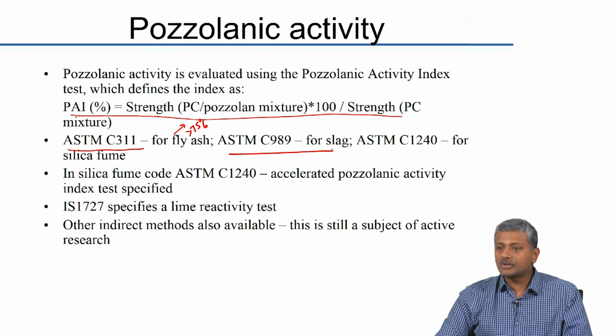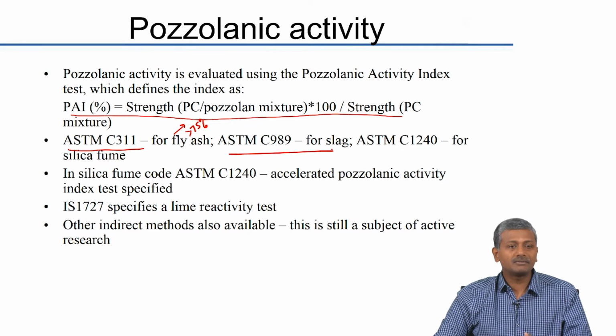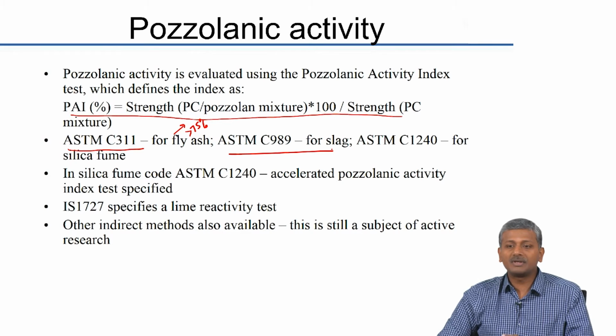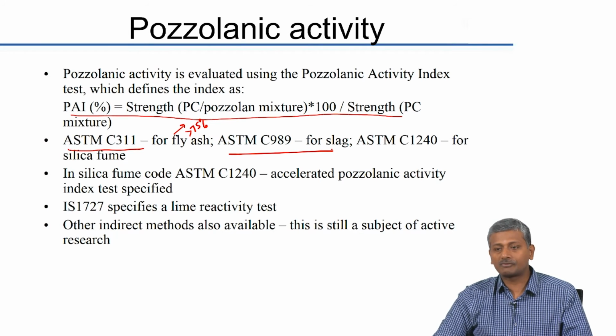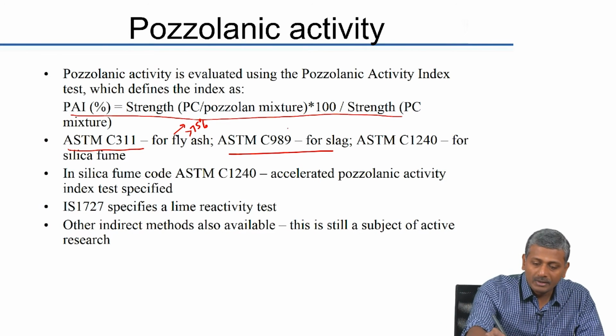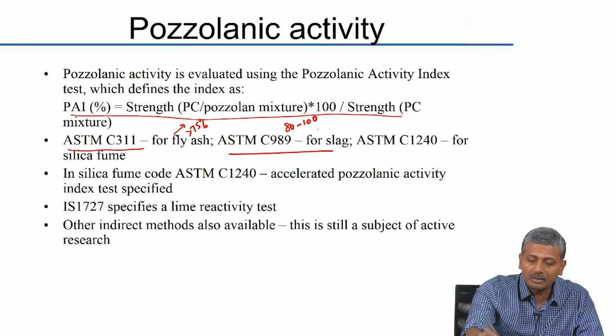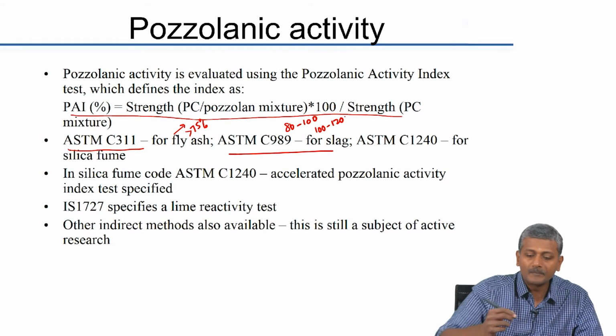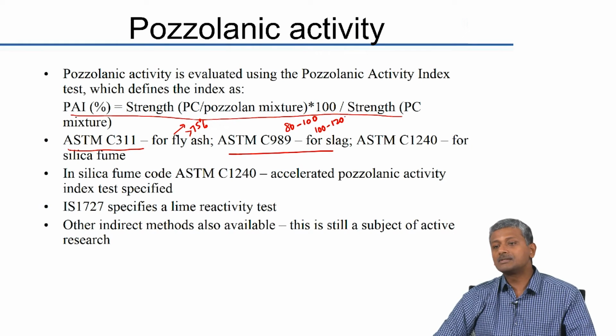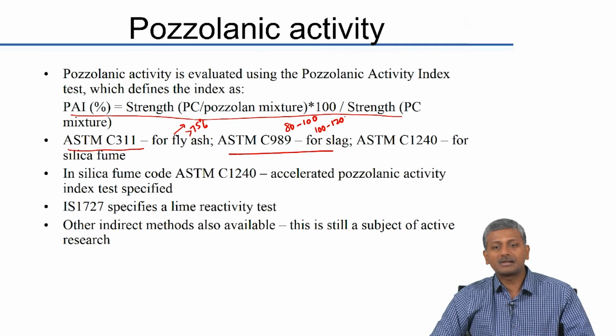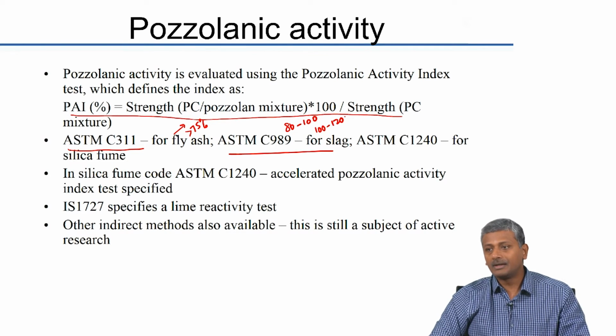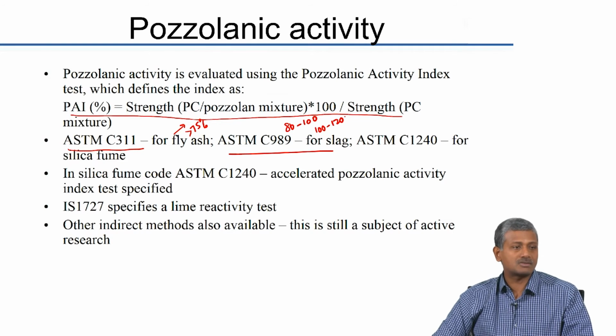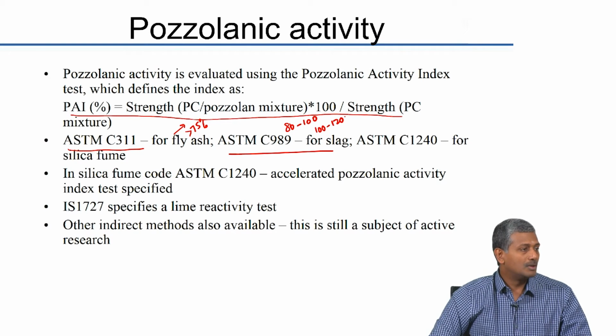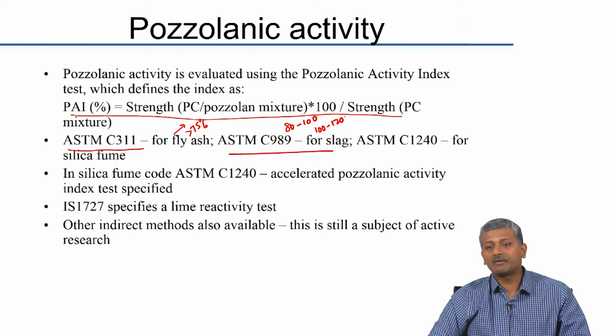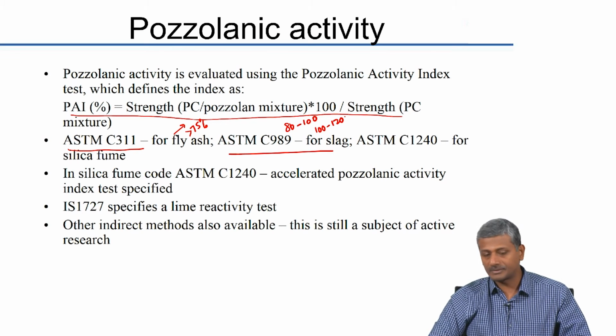Now, slag, because it is hydraulic and highly reactive, we use a slightly different means of classifying the type of slag. Slag is classified into different grades, 80 to 100, 100 to 120 and so on. That means the strength of the slag mixture is at least 80 to 100% of the strength of your ordinary Portland cement mixture, and 100 to 120 means the slag mixture has a strength greater than your Portland cement mixture. That means you have a very highly reactive slag in your system.